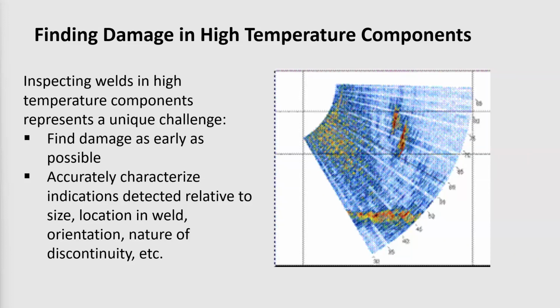It could be, for example, an initial flaw in the weld that was introduced during the welding operation itself. And if there's been no growth from that flaw, then that's an important piece of information that would be used in determining what the next step would be once the indication is detected.